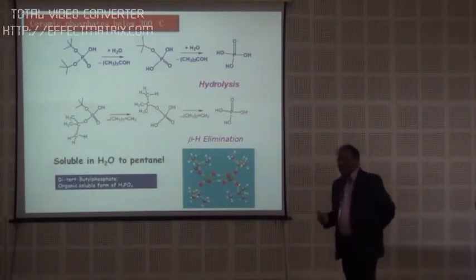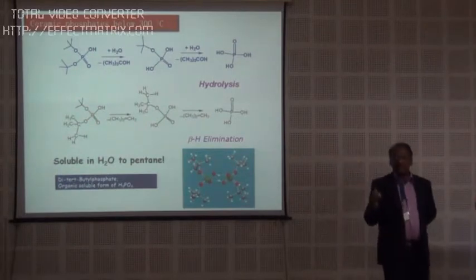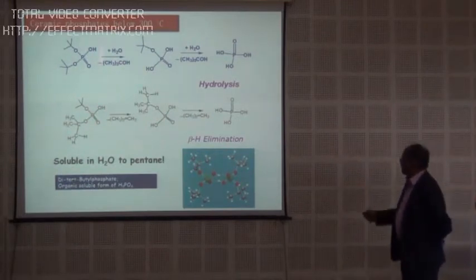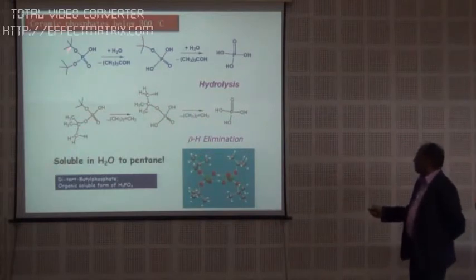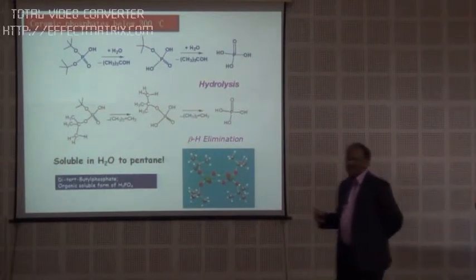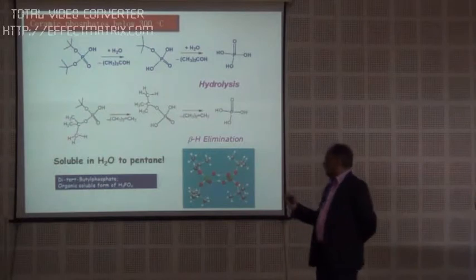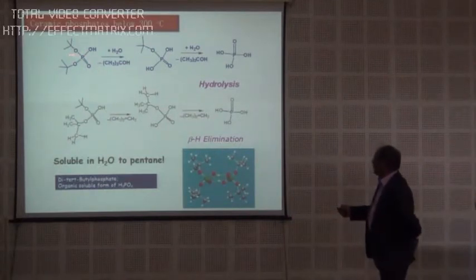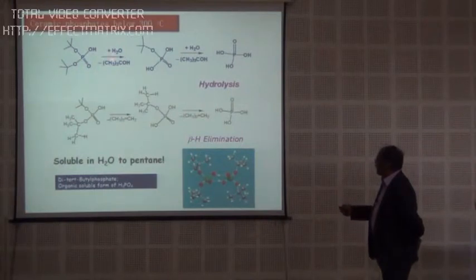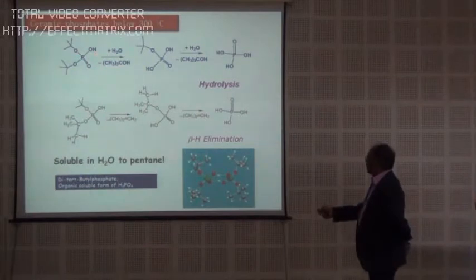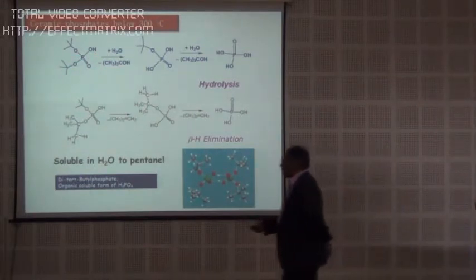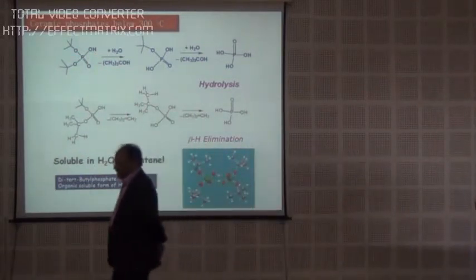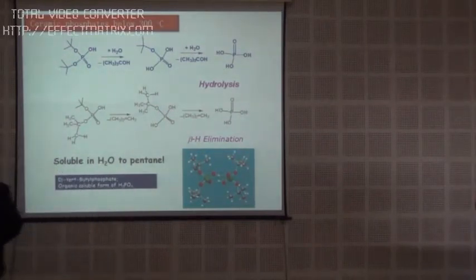So instead of doing reactions with phosphoric acid at high temperatures to make metal phosphates, why not start with this particular diester? Because it pretty much looks like a carboxylic acid. If you make a metal acetate from acetic acid, whatever happens there should happen with this, because only the carbon is replaced by phosphorus here. So on this part you can make a metal complex, and it is hydrophilic on this side of the molecule and hydrophobic on this side. As a result, this compound is amenable to synthesis in a variety of solvents, starting from pentane on one side to water on the other side.